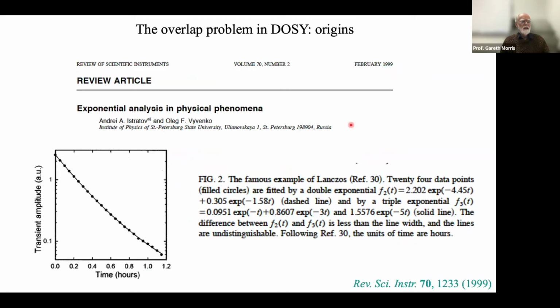Well, let's look at this problem of signal overlap that led to our initial quinine, geraniol, camphene one-shot spectrum giving so many peaks in the wrong places. There's a fundamental difficulty with exponential phenomena. If we add two similar exponentials, what we get looks for all the world like an exponential. There's an example here of a double exponential, which is virtually indistinguishable from a triple exponential. Now, I do recommend this very nice old review by Istratov, which explains a lot about the difficulty of disentangling superimposed exponentials.